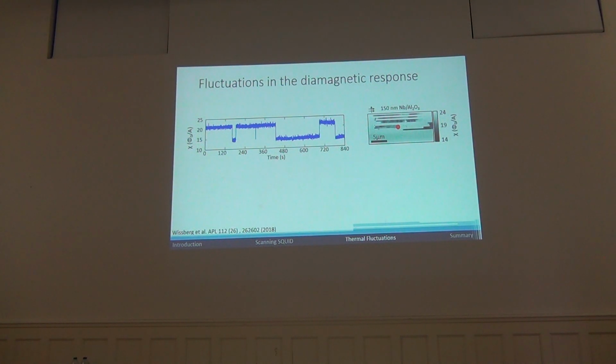These are actually how the superconductor fluctuates between two different abilities to shield itself from the magnetic field that we apply. So these are thermal fluctuations where we keep the superconductor close to the transition temperature without crossing it, and the horizontal streaks are how we image these fluctuations in the spatial image.